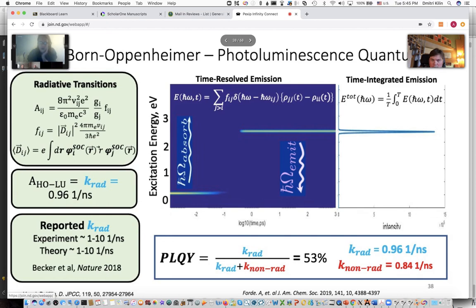And so during the dynamics, that's what this blue figure represents. Early in the dynamics, there are these low intensity IR transitions, which is this yellow bar around 0. And those just come from the carrier cooling. But once both the charges relax to the band gap energy, it emits very intense photoluminescence, which is shown in this very rightmost figure.